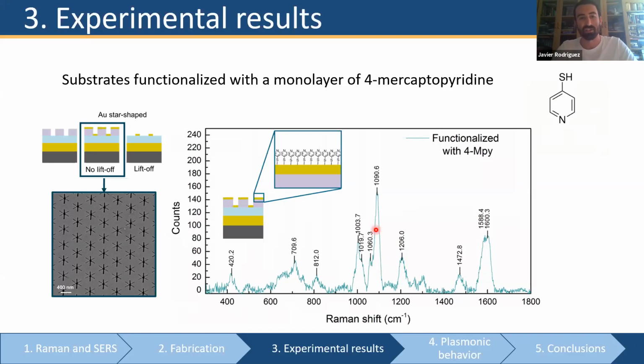This is just a functionalization of the surface of the substrate with a monolayer of this molecule. Here you can see a SEM image of the top of these structures, and you can even get to detect the same peaks.